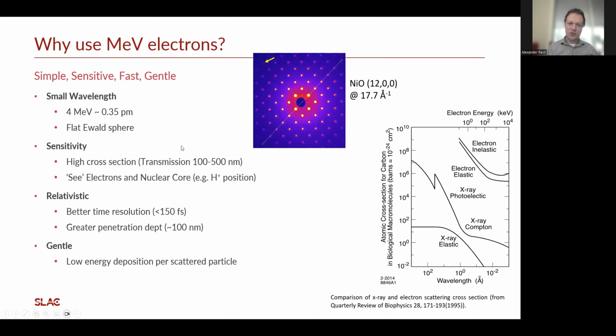Typically, for our transmission solid experiments, we're dealing with samples that are between 100 and 500 nanometers. That kind of stopping range can be as low as 100 nanometers, but depending on Z, it can move up to maybe about a half micron. But in general, we're dealing with thin film samples. On the beneficial side, this does mean that we can make measurements or get a lot of scattering even from things like single atomic layers. And that enables studies of these kind of thin film type heterostructures.